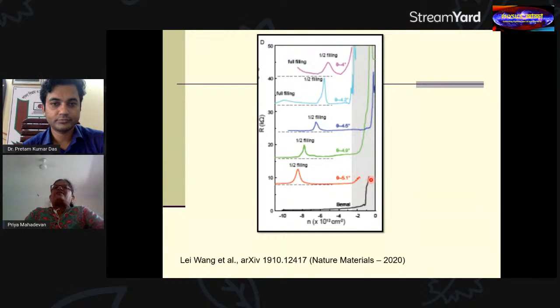What you can see is that, well, if I had my Fermi level in the gap, I would have a very high resistivity because it's a semiconductor. And as I introduce more and more holes into the system, my Fermi level is going to move into my valence band, and so I'm going to see metallic properties, and so the resistivity drops. And this is what it is.